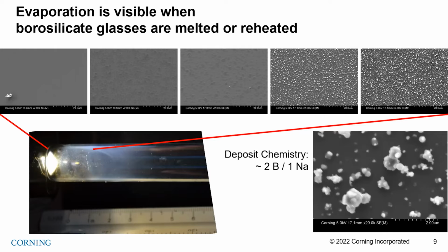But between those, the glass temperature was just right, where material was depositing, but it was also being reheated enough where it was actually starting to melt back into the surface. And it's that region where these defects are most likely to occur. So if you've ever seen bloom and then reheated the piece to get rid of it, what you're doing is reincorporating that sodium and boron into the surface and basically enriching and changing the glass chemistry significantly.